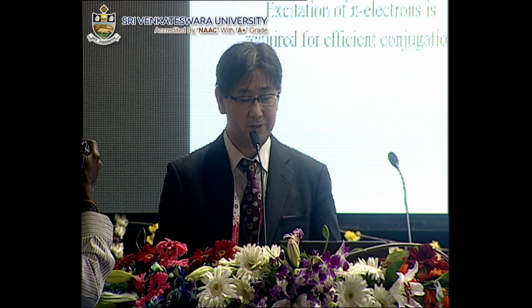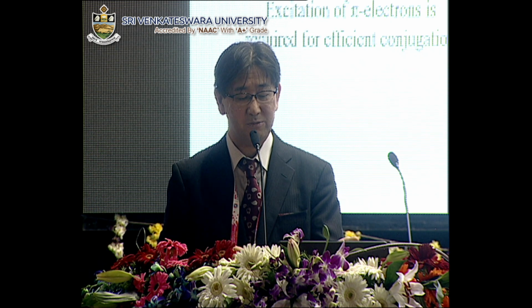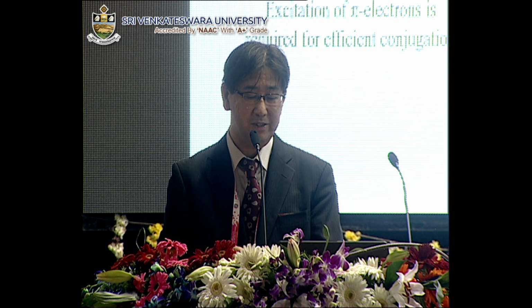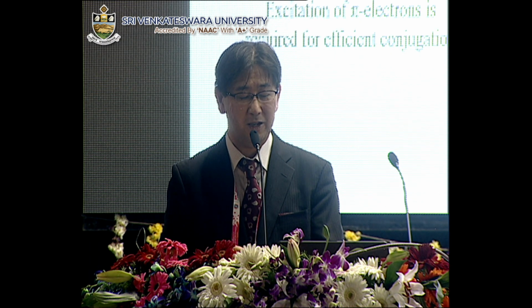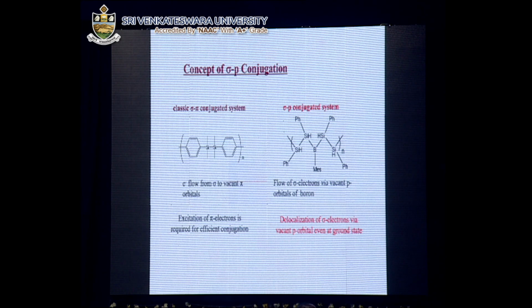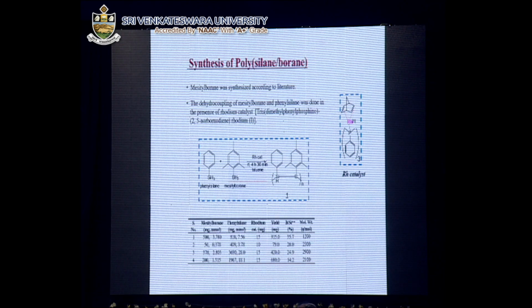The basic concept is that in the case of ordinary sigma-pi conjugation, when the aromatic moiety is photoirradiated, the original pi level is excited to the pi-star level, and to the original pi level, the electron flows. However, in the case of sigma-p, due to the inherent p orbital on the boron atom, such a conjugative interaction happens even at the ground state. Such a polymer was prepared for the first time by a dehydrocoupling reaction between phenylsilane and mesitylborane.